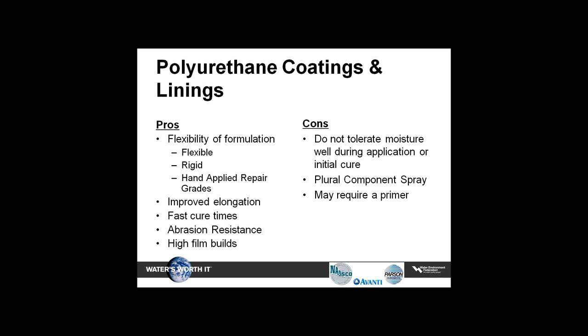Talking about polyurethane coatings and linings, the pros are flexibility. They're very flexible, 50, 60% elongation. There's also rigidity in their film, which is kind of an oxymoron with something flexible also being rigid. It can be hand applied with certain technology, but it has very good elongation, fast cure times, and very good abrasion resistance. And again, up to a 1/4 inch or high film builds.